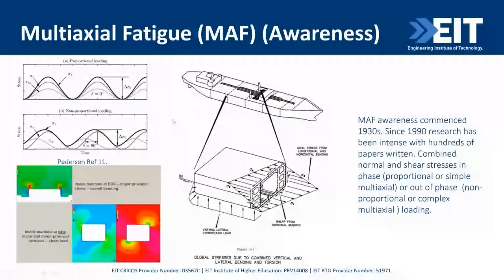So multi-axial fatigue is again about awareness. All of the previous fatigue has been uniaxial fatigue, where one direction's stress range is highest. The obvious multi-axial case is the ball mill with that square manhole at 90 degrees, at the side. It'll be under shear at the corners, and then when you get down to the bottom, you'll be under normal stresses. That's the typical situation with non-proportional loading, your shear 90 degrees out from your normal. And ships are in the same boat.